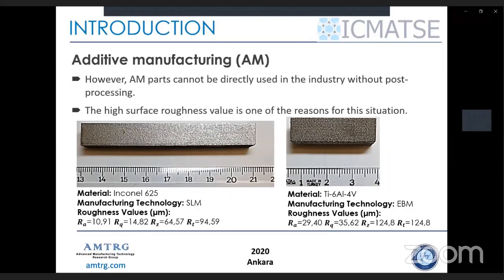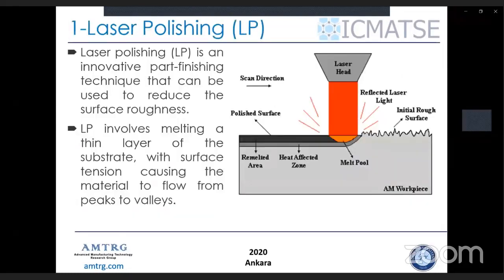Uncontrolled surface roughness could significantly affect the fatigue life and the crack initiation. So, laser polishing is an innovative part finishing technique that can be used to reduce the surface roughness by melting a thin layer of material on the part surface. Laser polishing involves melting a thin layer of the substrate with surface tension, causing the material to flow from peaks to valleys. In laser polishing, the material is not removed, but is relocated as a molten pool.